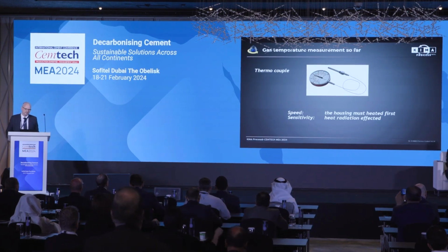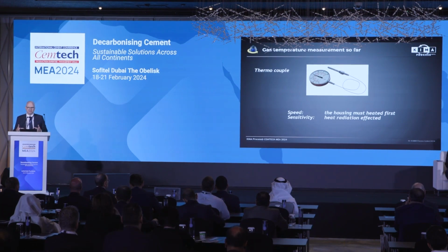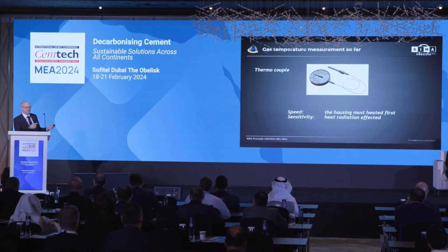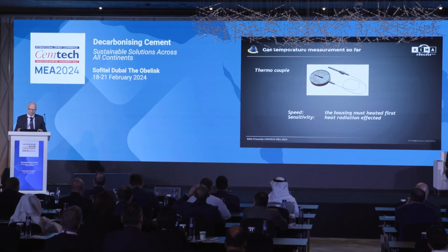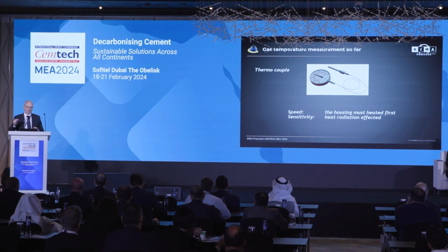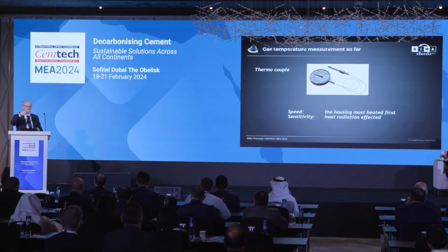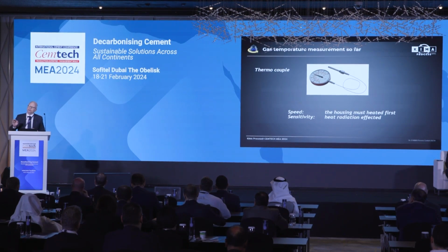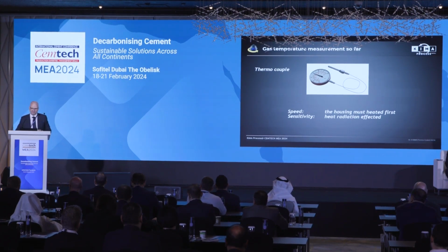Look, thermocouples are very, very slow, because the housing of this sensor must be heated up first until the measurement itself can give out a change to the control system. Delay time. We come to that later. The other thing is, it's not a non-contact system. It's a contact system. So if you put such a finger, let me call it that, inside this combustion room, you will have an effect of the infrared radiation. And this infrared radiation from clinker and from flame does not allow you anymore to measure the pure gas temperature. An acoustic measurement principle is completely different.